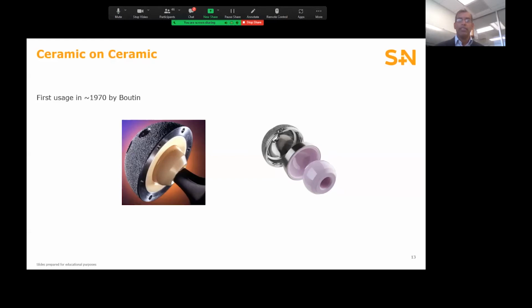The image on the left displays a device that incorporates alumina, while the image on the right displays zirconia toughened alumina for both the head and the liner. So these designs are incorporating very small diametric mismatch between the two articulating surfaces, which helps promote fluid entrainment.